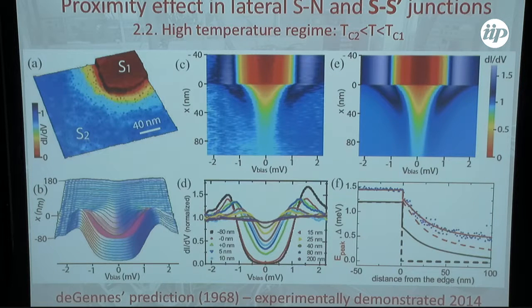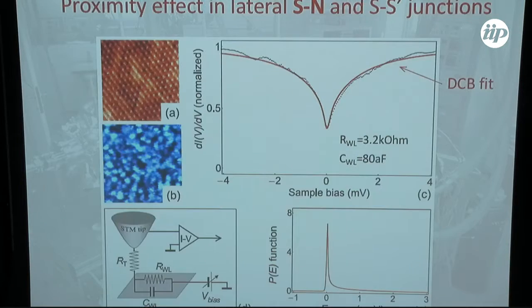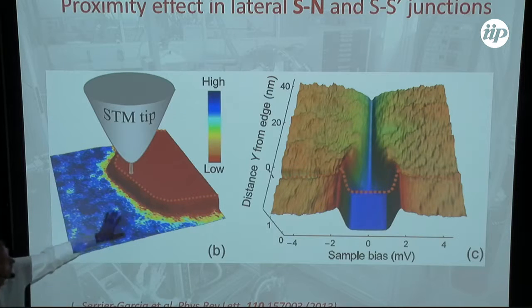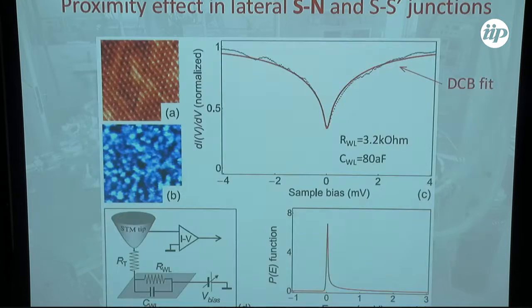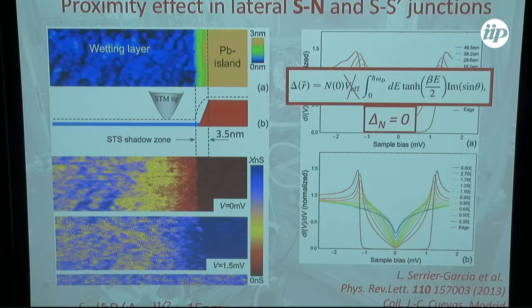While if you use a superconductor and here just a metal which doesn't have any attractive electron-phonon interaction, you will induce Andreev quasiparticles here, but no superconductivity. So there is a clear difference, and it comes from the fact, I can show you the self-consistent equation in any theory, Bogoliubov-de Gennes or Usadel, whatever, that the superconducting order you induce by proximity is always proportional to V effective. So if V effective is 0, you will induce correlations, but delta will be exactly 0. It is not because you have a proximity effect that you have superconductivity. You always have superconducting correlations, but you don't have Cooper pairs.